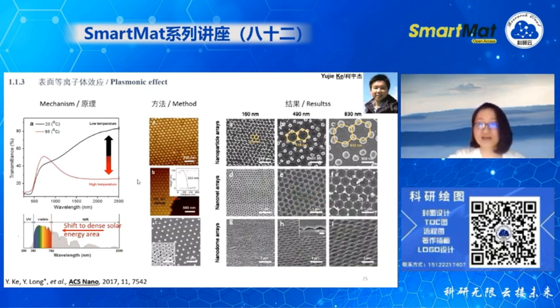Okay, and the other thing is vanadium dioxide also has a very interesting, we call it tunable plasmonic effect. People who are doing plasmonics know plasmonic only occurs in the metal state, am I correct? But vanadium dioxide, as I said before, is a near room temperature phase transition material, because it can change from metallic to insulator. Which means this plasmonic effect can also be tunable.